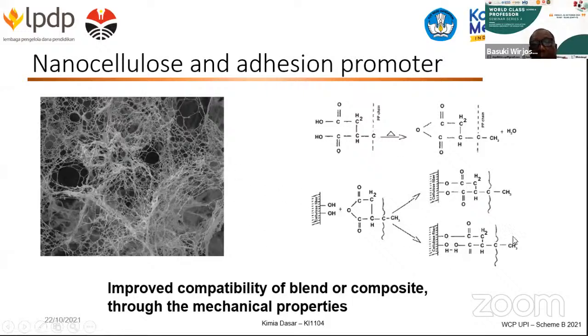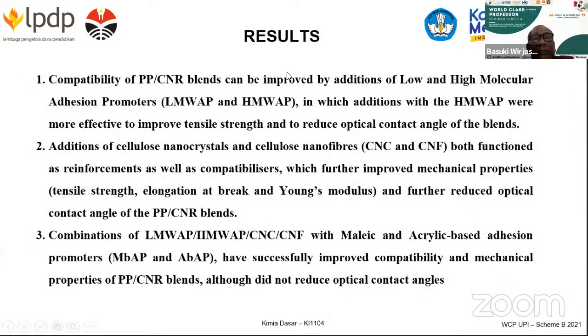As we improve this, we get a very good improvement in mechanical properties, and this is the result we have got. We introduced low and high molecular weight promoters, based on maleic, as I mentioned before. When we put them into the polypropylene and cyclic natural rubber blends, we can see improved tensile strength, and the second thing is reduced contact angle.